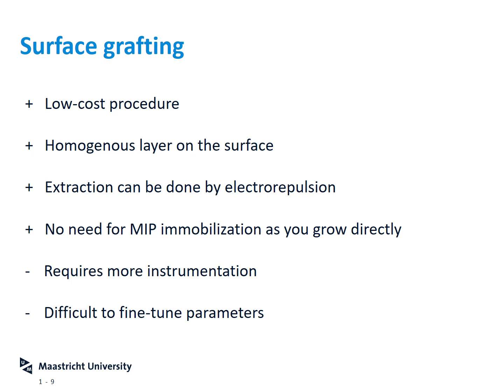You will get a very homogeneous layer on the surface. You can do the extraction by repulsion. Let's say you make an imprint of a negatively charged particle by just placing a positive potential over your electrode. You will push the target out again, and you don't need to immobilize your MIP because you grow it directly onto the surface. The disadvantage can be that it requires a little bit more instrumentation, especially electropolymerization, and it's more difficult to fine tune the parameters. So it's a little bit more difficult to understand when you should stop cycling in electropolymerization, or what type of molecules you should immobilize on your surface. So the actual reaction parameters and controlling them is more complicated.